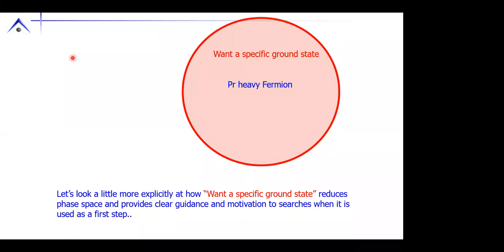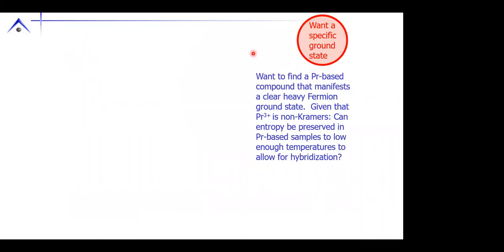Let's go to the other motivations because these are where things become more interesting. So I want to give two examples of what I would call negotiating with nature, of wanting a specific ground state and using that desire to then try to narrow phase space. So let's start with a desire to have a praseodymium-based heavy fermion, okay? So praseodymium is an interesting material. It can be ambivalent. If you look at the oxide, it's a mixed valent oxide. It's a mixed 3+, 4+ oxide, okay?